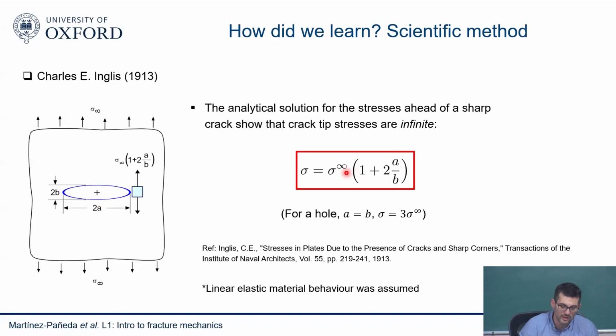And then the other thing you realize is that if my ellipse is quite sharp, if B goes towards 0, my stresses at the tip of my ellipse are going to be infinite. That was puzzling to a lot of people because, of course, there's nothing completely, atomistically sharp. But some defects, particularly in brittle materials such as glass, as we discussed before, can be very, very sharp, to the point that B could be tiny, nanometers long. And if this is nanometers long, this means that a tiny applied stress will lead to a very, very large crack tip stress. So this was a problem.